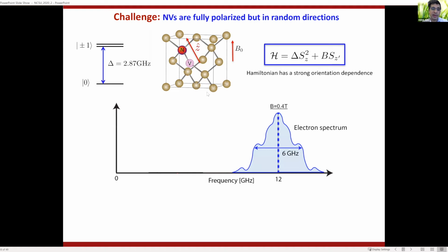So another way to say it is, when you look in frequency space, the electronic spectrum of these NV centers is very broad. So it's orientationally broadened. And this is true for any spin 1 electron or spin 1 spin in general. You've got a very large anisotropy. So the spins are very broad, and it's very difficult to control them. Even in a modest field, you've got a many-gigahertz coupling spread in the electronic ESR spectrum. So it's very difficult to control these spins.